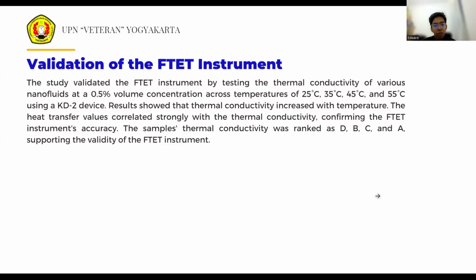Validation of the FTET instrument. The study aimed to validate the FTET instrument by testing the thermal conductivity of various nanofluids with a 0.5% volume concentration. Four nanofluid samples were tested at temperatures of 25, 35, 45, and 55, using a KD2 device for measurement. The result showed an increase in thermal conductivity with temperature for each sample.